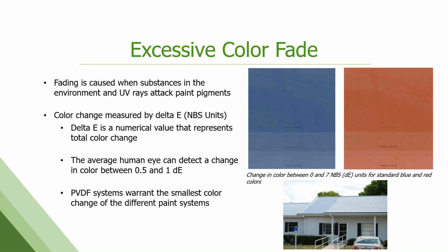Likely cause is either they've intermixed paint systems, right? So they have a poly and a PVDF on the same roof, or an S&P and a PVDF on the same roof that are weathering differently. They've used different paint suppliers and mixed them on a roof. Or it could be due to film thickness. The faded panels there may not have been in spec for film thickness and therefore are degrading quicker than the material that was in spec. So a lot of root causes for why we'll get fade.